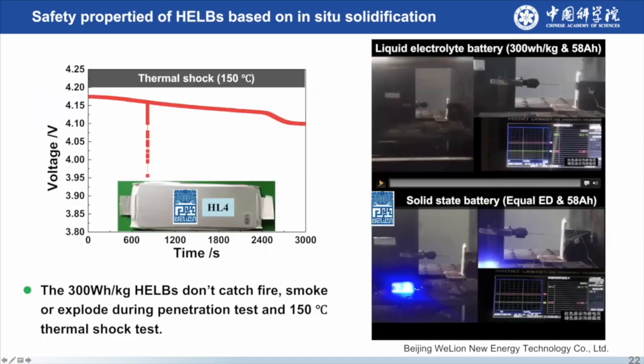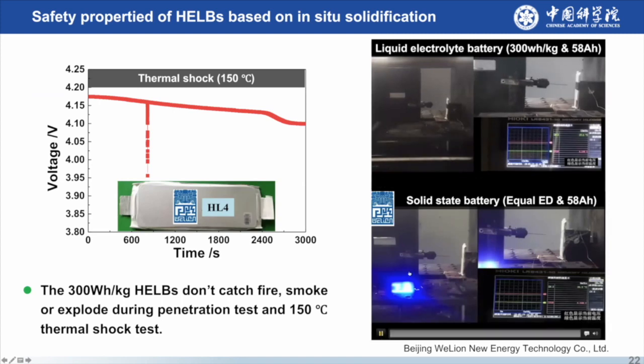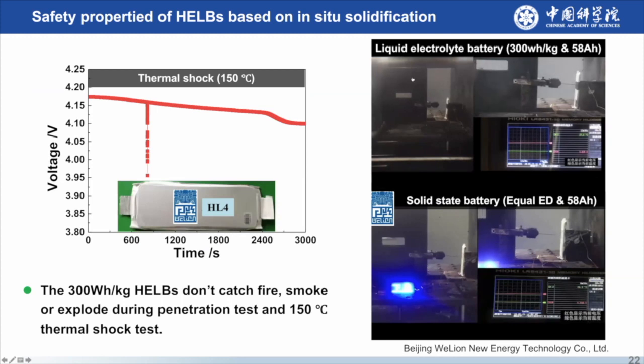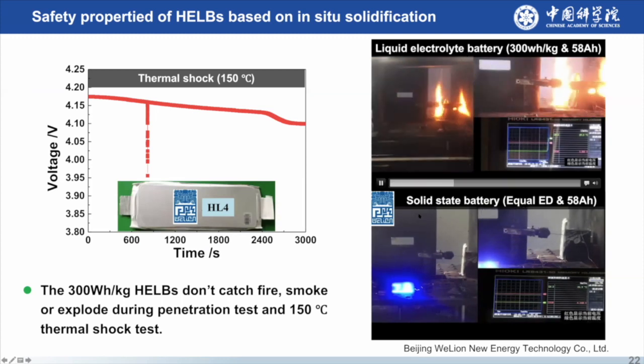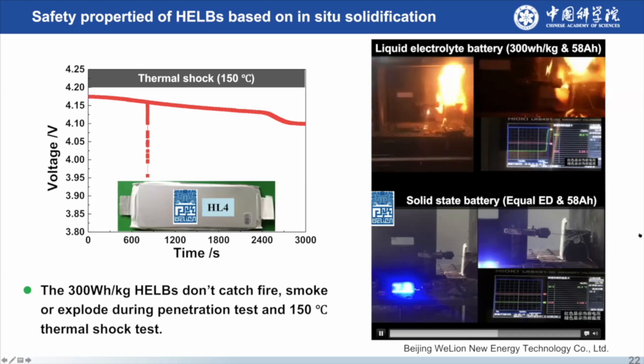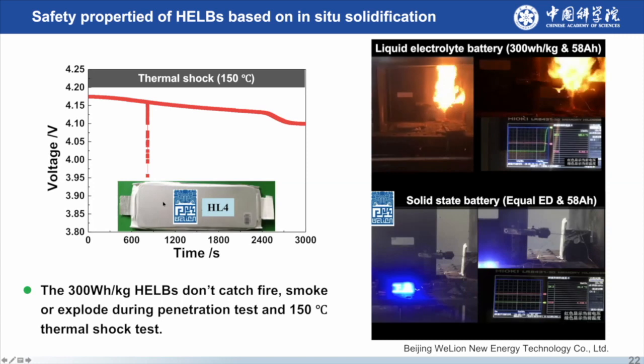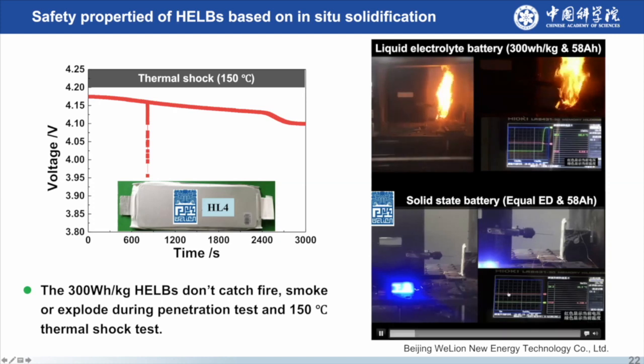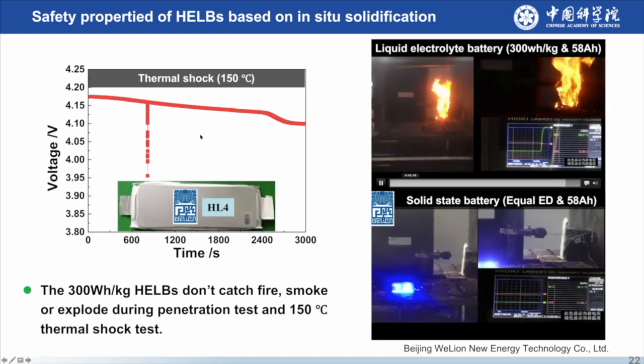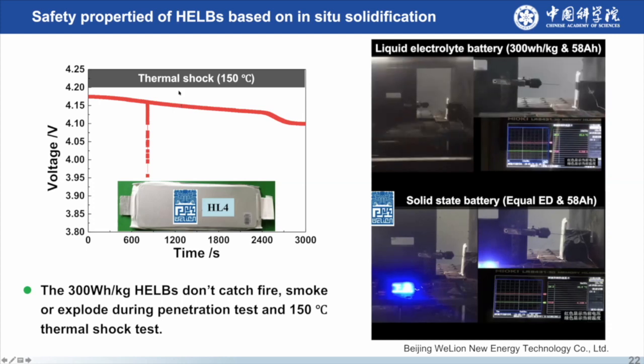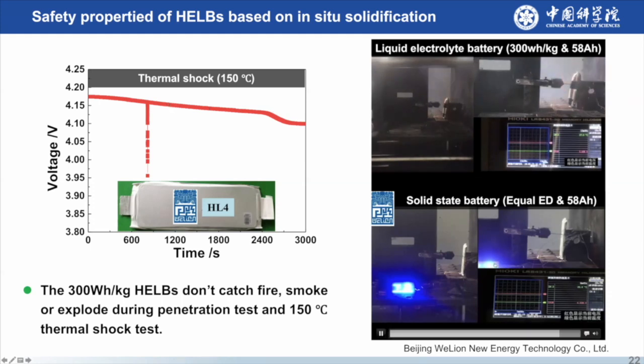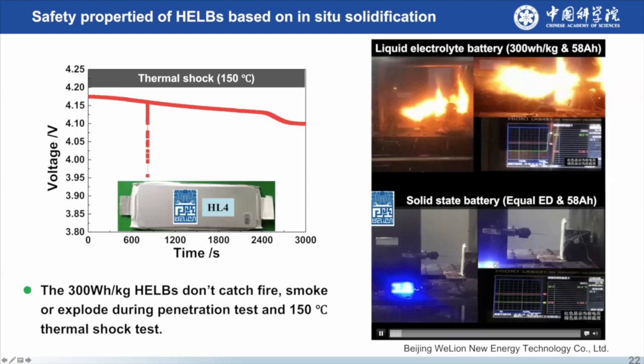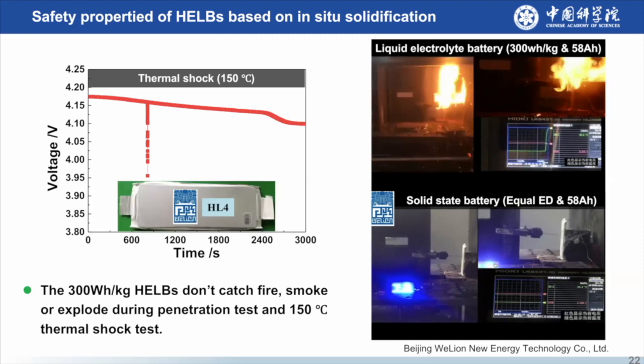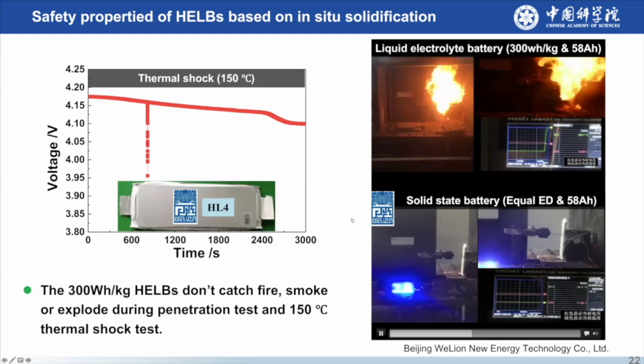And the very important thing is the safety issues. So with this combination comparison, you see the liquid one and the hybrid solid one. So for the hybrid solid one, for this pouch cell with a large capacity, all the samples have passed the nail penetration. This is very difficult for high energy density cells. And also for the thermal shock testing, you can see it can pass without a significant voltage decay. And even for this nail penetration, the customer has tested that all the cells have kept the voltage when we do the 100% SOC nail penetration testing.